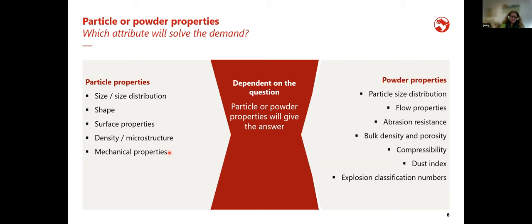Sometimes it's difficult to distinguish between particle and powder properties, especially for mechanical properties. For very small particles it's not possible to measure mechanical properties directly, so we go to powder properties and look at abrasion resistance, flow properties, or compressibility to characterize the mechanical properties of particles indirectly through powder behavior.